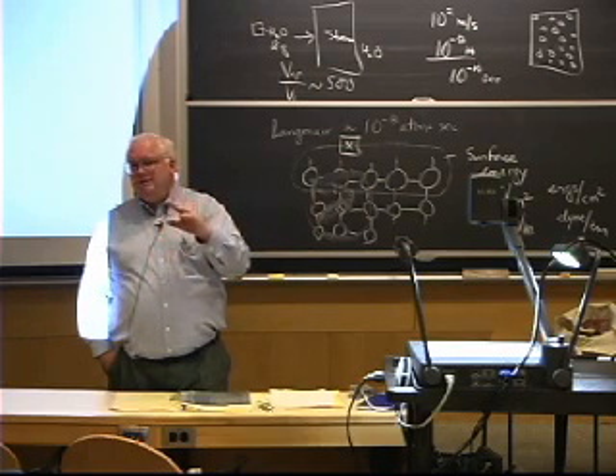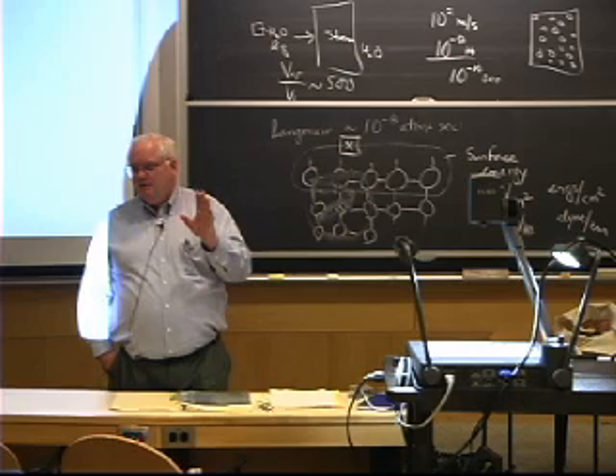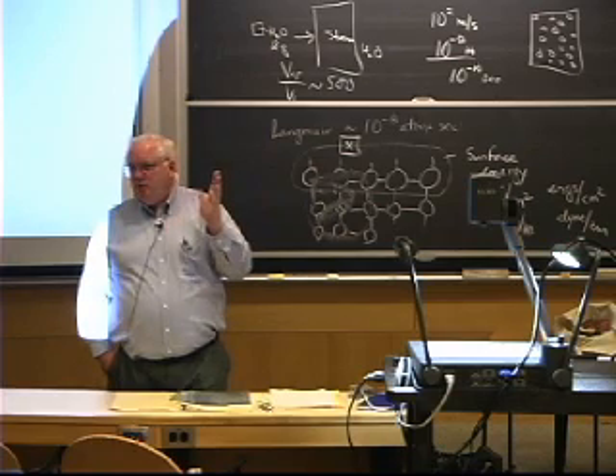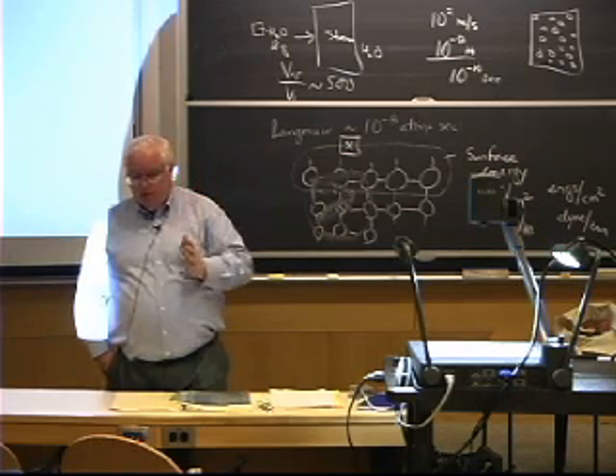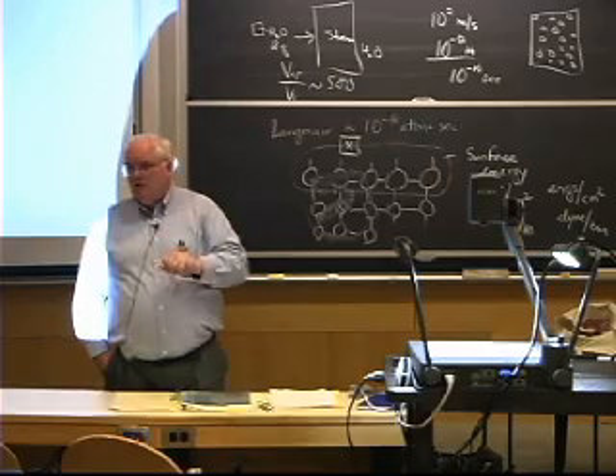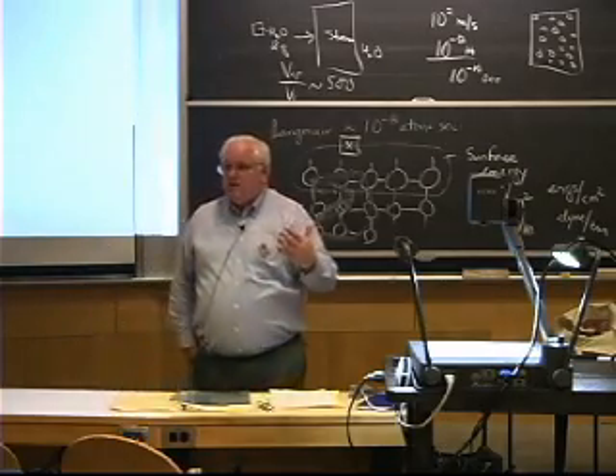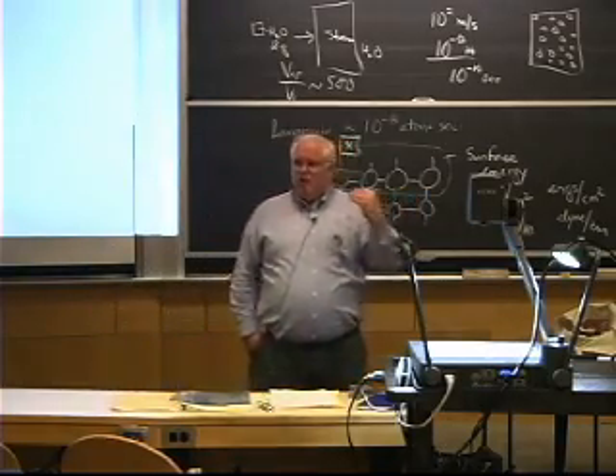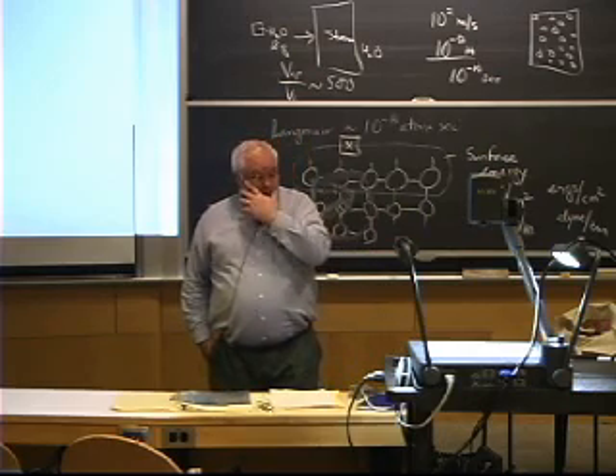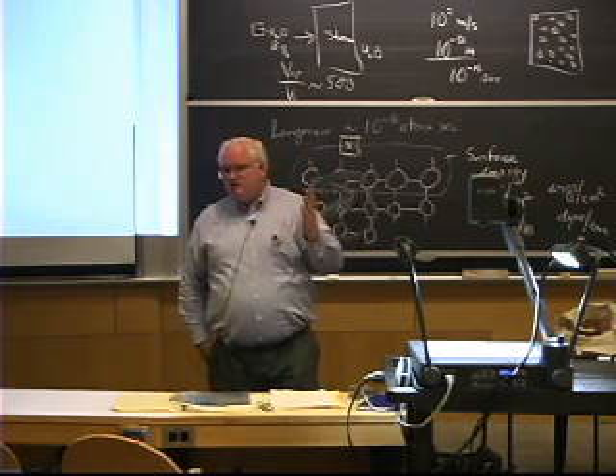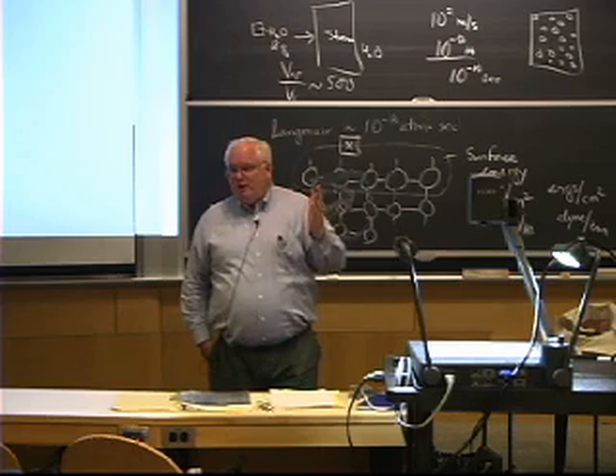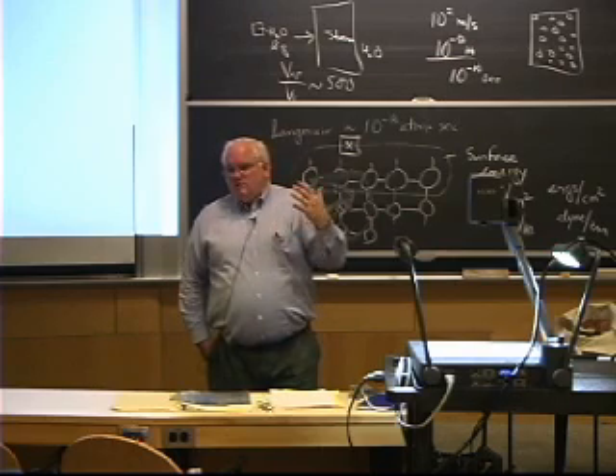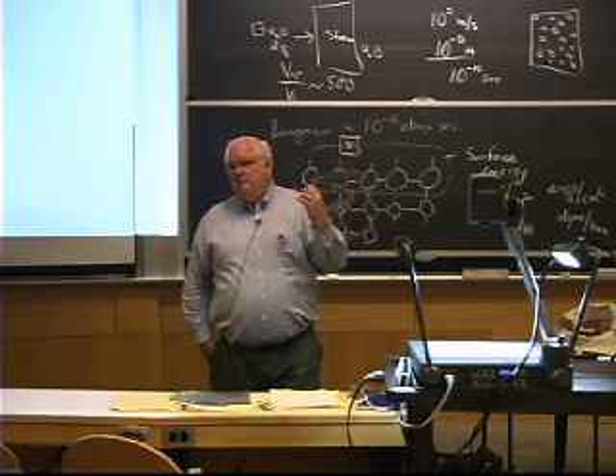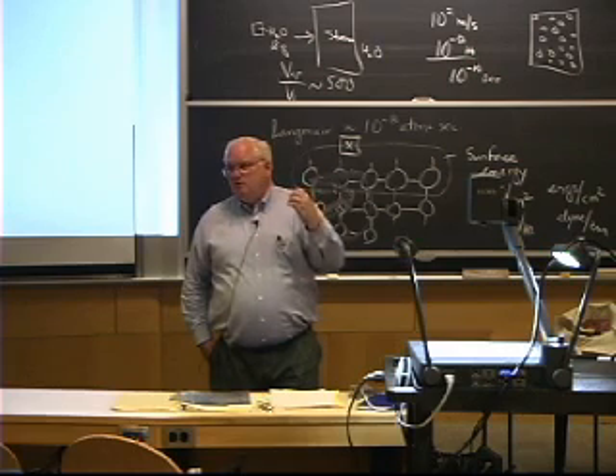Aluminum and magnesium will not dissolve their own oxide. The solubility of oxygen in metallic aluminum and magnesium is near 0. And as a result, you have to get rid of the oxide layer. But that aluminum oxide melts at over 2000 C. Magnesium oxide is 2800 C. So there's tremendous strength to that oxide layer, and it's not easy to get